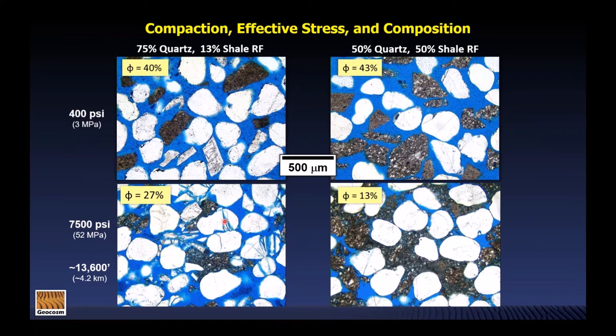So in thinking about modeling this, what we've found through a lot of experiments, in particular that Dick Larice, my colleague, has done, is that there's a strongly nonlinear effect of the compaction magnitude on both the volume of ductile components in the rock and their mechanical properties, such that the more mechanically weak they are, the more strongly nonlinear the compaction effect is. And so we built models that try to account for that compositional effect and rock property effect in our system. So let's talk about quartz cementation now.